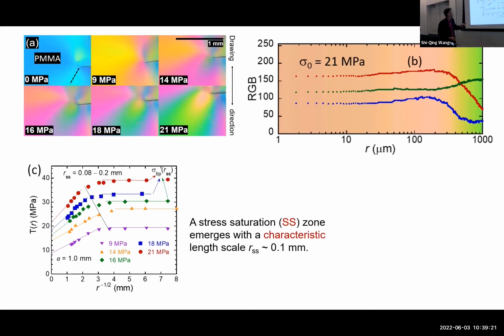And you can quantify this information. The stress builds up, because I plotted it as square root of 1 over R inverse, so toward the tip is this way. It builds and then levels off. And I pray to God, meaning indeed we did probably, that it levels off at a scale that we can resolve: 50 microns, 100 microns.